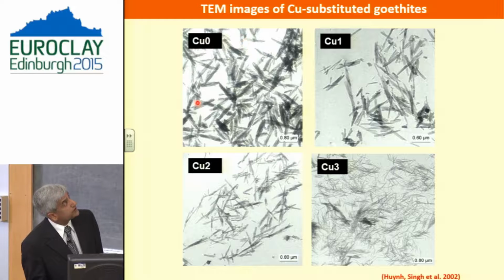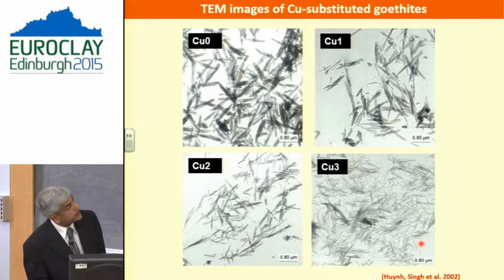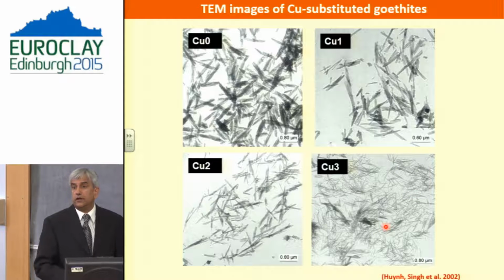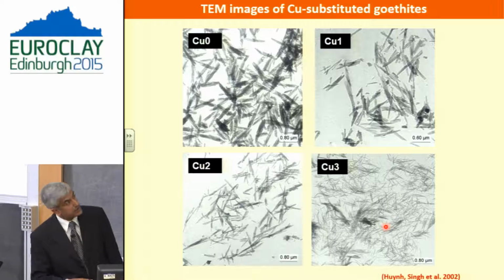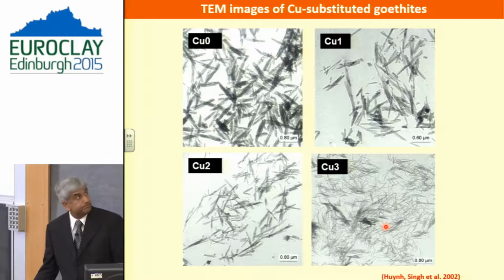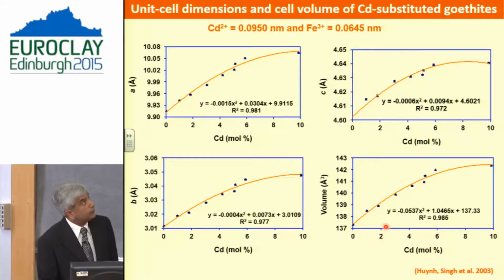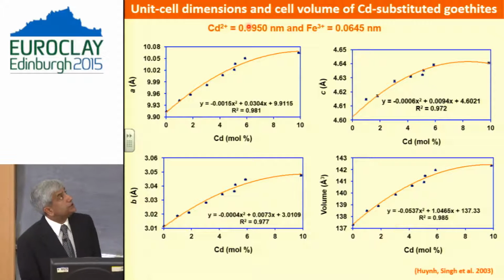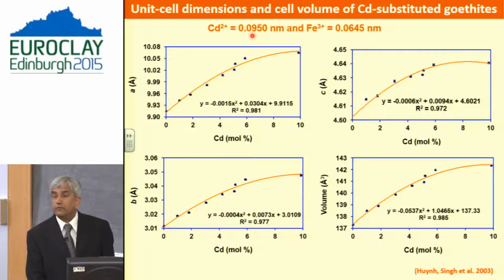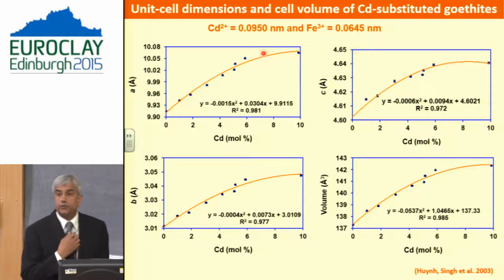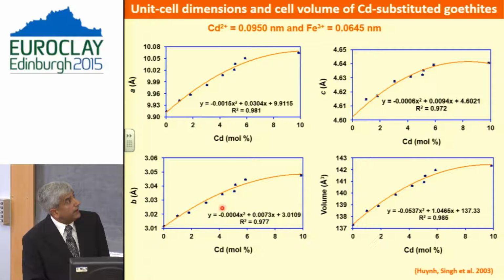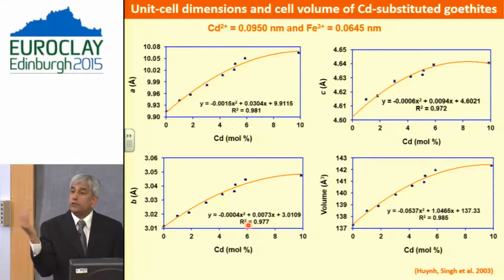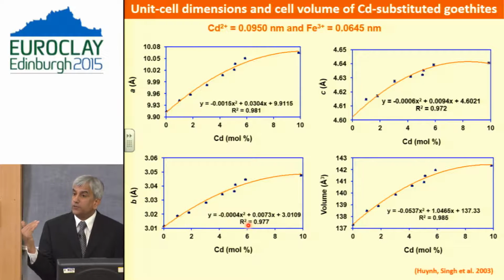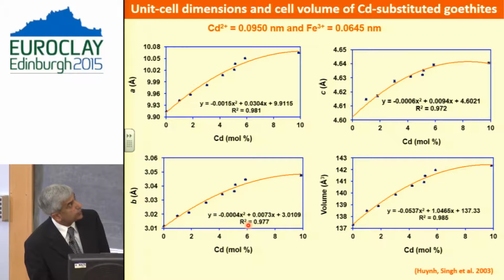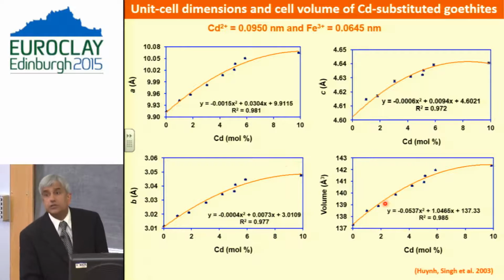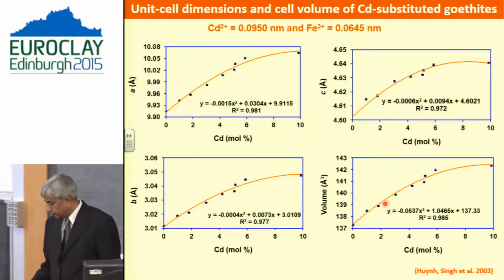When you look at the structure, this is pure goethite, and that's the 3 mole % substituted goethite, where you can see the particles become much thinner and smaller in size. We also looked at the substitution of cadmium, which this time is very large, 0.0950 nm compared to 0.0645 nm. One thing is that we were able to substitute a much larger amount of cadmium in the structure, up to about 10 mole %, and all 3 dimensions increased with the increasing substitution of cadmium.